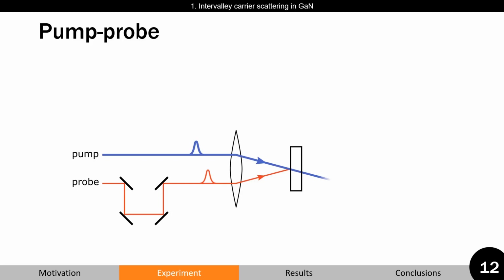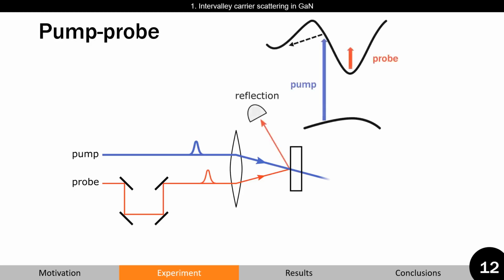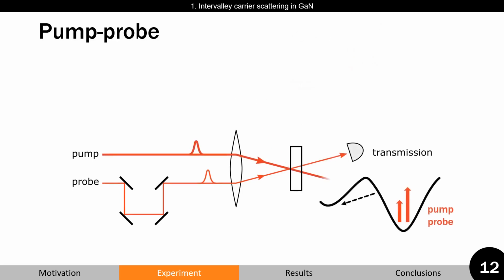In this study, two pump-probe configurations were used. In differential reflection, intervalley carrier scattering was induced with a UV pump, while electron relaxation was monitored with an infrared probe. In the differential transmission measurement, both pump and probe pulses were in the infrared and near infrared range, so that only states in the conduction band could be probed.